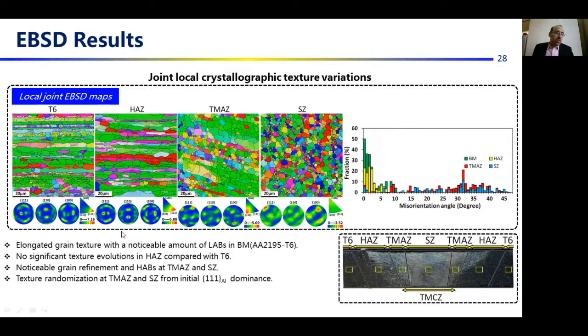From the EBSD results, we see the elongated grain texture with a noticeable amount of low angle grain boundaries at T6 condition because of the high plastic deformation during rolling, and no significant texture evolution in the HAZ compared with T6 under the thermal effects of the FSW, and noticeable grain refinement and high angle grain boundaries at TMAZ and at SZ at the joint center because of high recrystallization and plastic deformation, and texture randomization is also observed from the dominance of 1-1-1 planes at the BM. You can see completely randomized texture in the SZ.